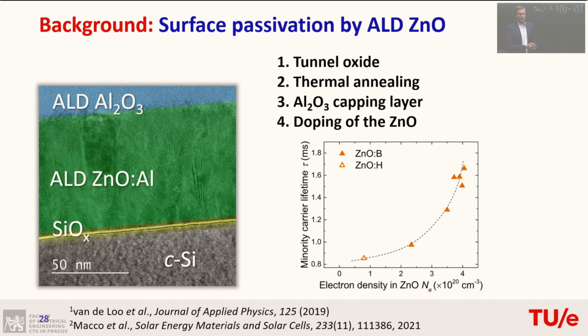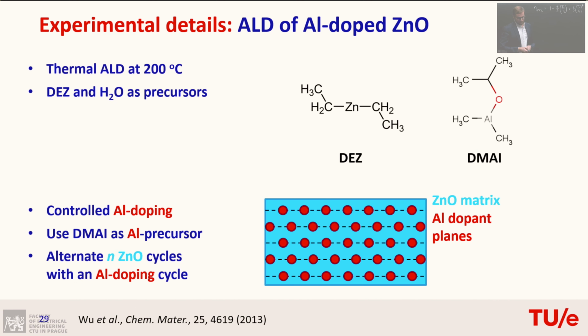So these are the four ingredients that you need to make passivating zinc oxide with doping. So how do we actually make this? We use, again, an ALD process. In this case, it is a thermal process, so that means you dose your TMA, and then afterwards you dose water. For the zinc oxide, we use diethyl zinc as a precursor, and then you get a matrix that looks a little bit like this. So you have a zinc oxide matrix, and in between you have planes where you have aluminum. And this is the way you make doped materials with ALD typically.